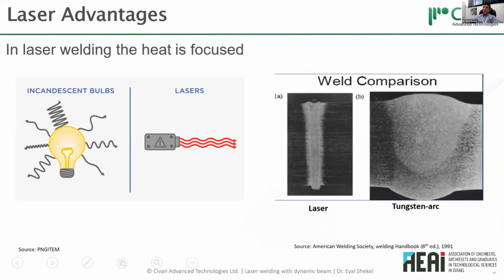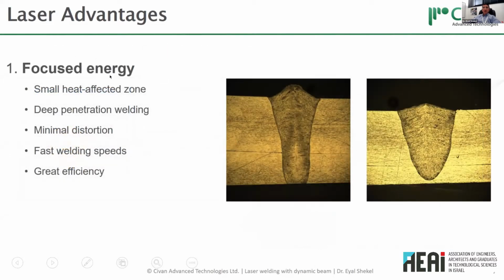And the result is that when you use a laser for welding, all the energy is focused and all the heat is concentrated, and you can get a very well-defined, narrow weld, compared, for example, to a tungsten arc, where the heat is spread over the weld and you get a much broader weld. So that results in a few advantages. First of all, the fact that all the energy is focused means that you have a very small heat-affected zone. You can get a much deeper penetration. The overall part has much smaller distortion. You can get to faster welding speeds, and you are much more efficient using your energy.